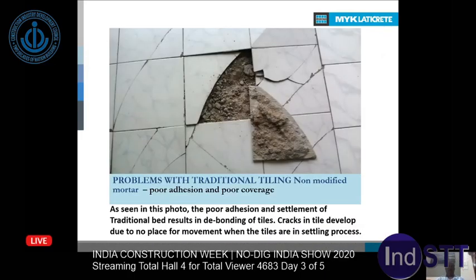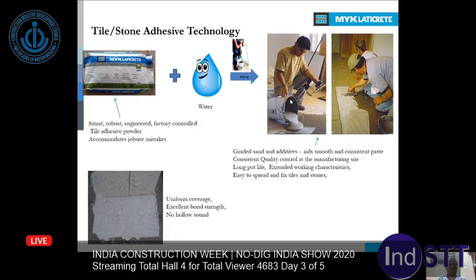The moment tiles start cracking, you see this kind of situation. This is very, very common when you go with the traditional tiling systems. That is because the cement is not there or a good amount of adhesion is not there. Now, all the water is taken by this sand cement bed. There is no water available for the cement curing. Then obviously coverage is very, very poor. Then it's a hollow sound. The moment you give a little force, the tiles will start cracking.